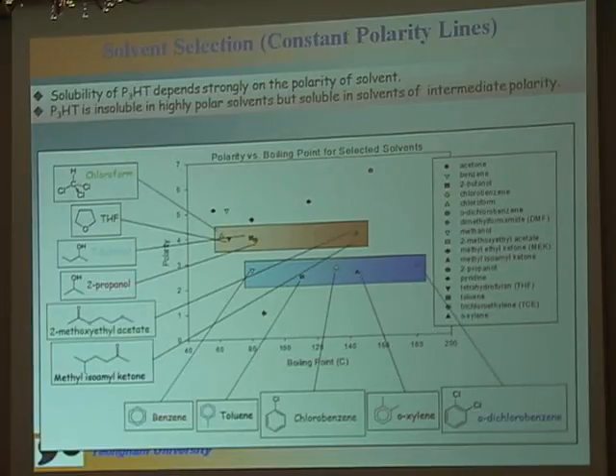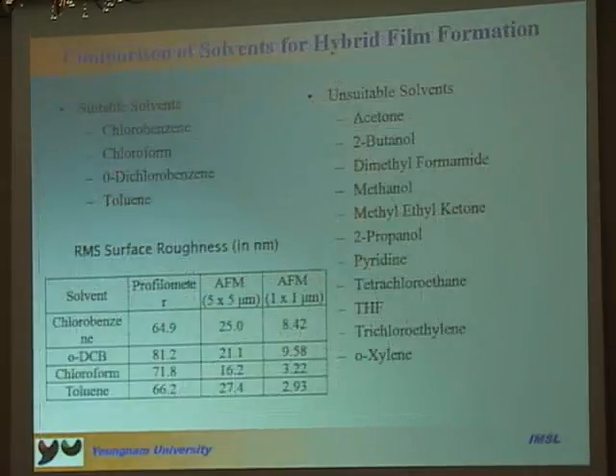We investigated solvents by polarity and boiling point. So we observe the best solvents for use in our experiment: suitable solvents in this column and unsuitable solvents in this column. And finally, we also investigated surface roughness with different solvents. So we found that chlorobenzene, DCB, chloroform, and toluene were chosen for our experiment.